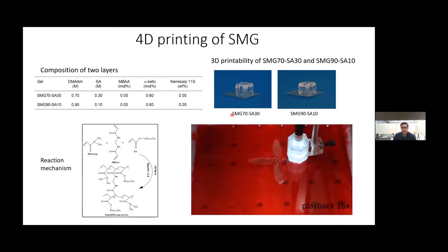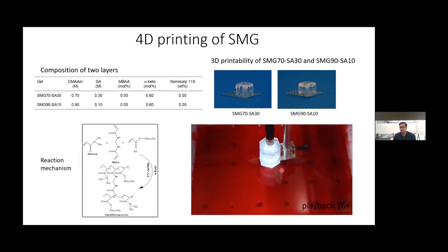For 4D printing of these shape memory hydrogel materials, I have chosen two different compositions. You can see this is SMG 70 SA30, which represents 70% of DMAA concentration and 30% of SA concentration, that means stearyl acrylate concentration. And another one is SMG 90 SA10, where DMAA concentration is 90% and SA concentration is 10%. And here is the image of the 3D printable shape memory material. And this is the 4D printing of the flower, the 4D printed flower. First, I have printed the first layer and then changed the solution and then printed the second layer.